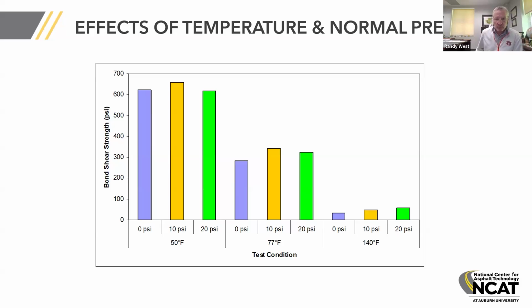At 77 degrees, we got an effect of a lot of the factors. It wasn't so sensitive here to the normal load. That's the 3 different bars at 77 in the middle. And at 50 degrees F, so at lower temperatures, there's very high bond strength unless there's some debonding occurring.